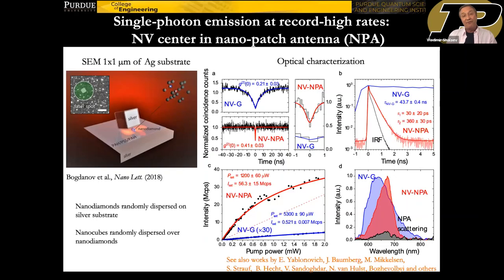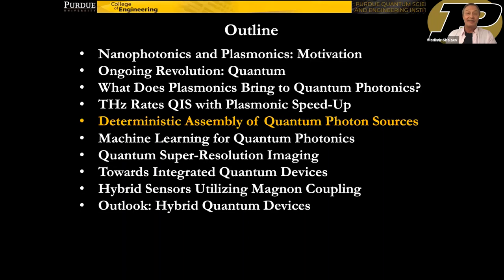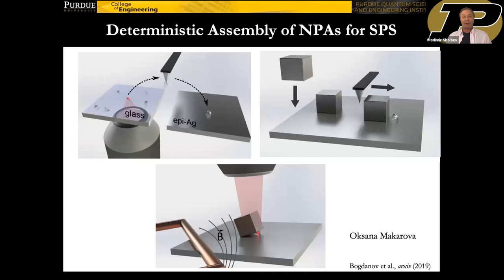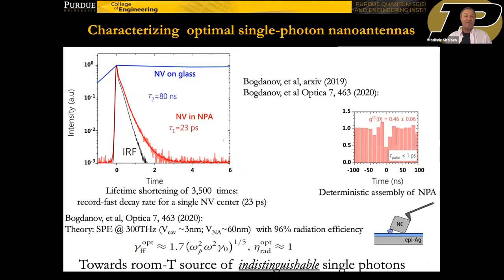And the next step to further increase the enhancement provided by the plasmonic antenna is to use deterministic assembly. So in this approach, we first place these nanodiamonds with nitrogen vacancies on a glass substrate. We characterize them, we find really good sources of single photons, bright and stable. And then you pick up that particular nanodiamond with a tip of an AFM and bring it on top of an epitaxial silver film. Then you place a silver cube in a nearby area and push it with a tip of the AFM so that it climbs on top of this nanodiamond. And in the end, you have this nanodiamond sitting at the edge of your nanocube where the Purcell enhancement is the largest. And you get really strong Purcell enhancement in this case. And the results, not surprisingly, are by far more impressive in this case.